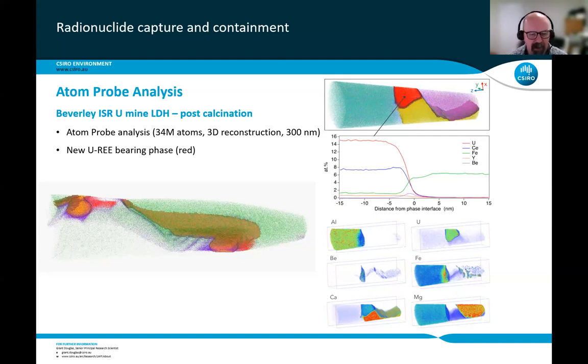And the really interesting thing about this as well, you can see a little blip just above 0 there that is actually beryllium. And if we look at that, we can actually see beryllium here in the purple in this image. If this will play for me, it's probably not going to play now, unfortunately. No, it won't, but so be it. The beryllium actually forms an interface, just an atom-thick interface, between that and where we see the precipitation of these uranium phases. It's just a really interesting little outcome from the work.